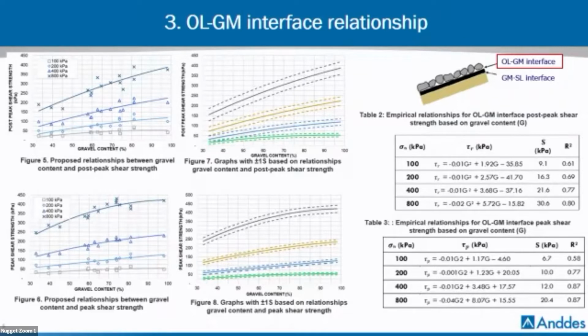In figure 5, we show the proposed relationship between gravel content and post-peak shear strength. In figure 6, we show the relationship between gravel content and peak shear strength. Figures 7 and 8 show the same relationships, but with lower and upper boundaries based on one standard deviation.